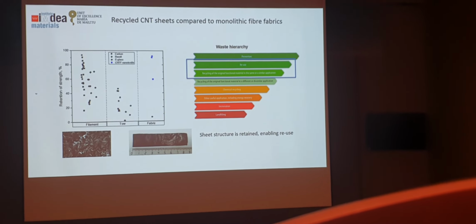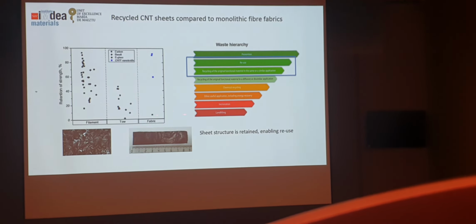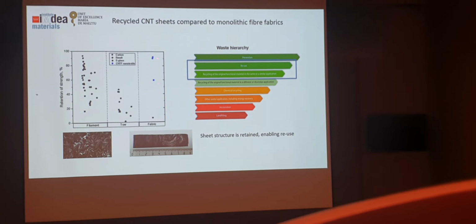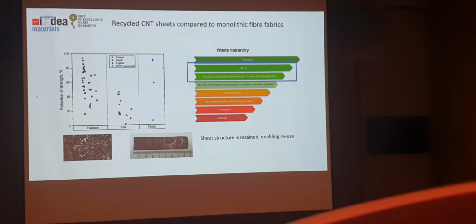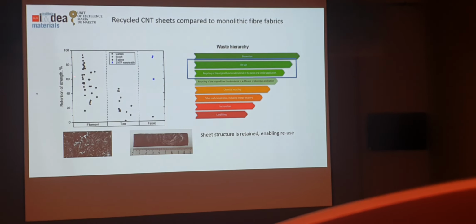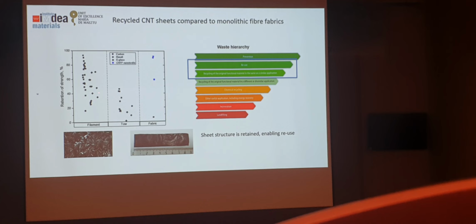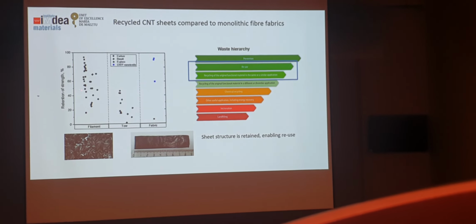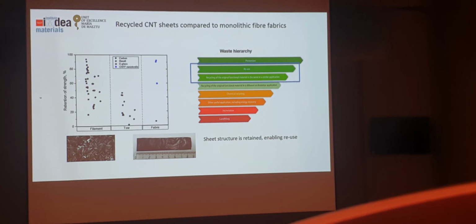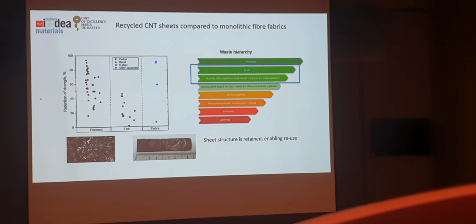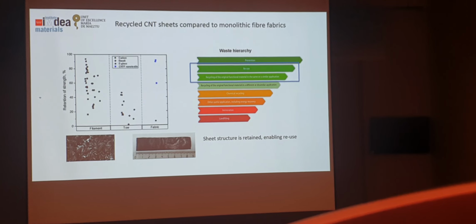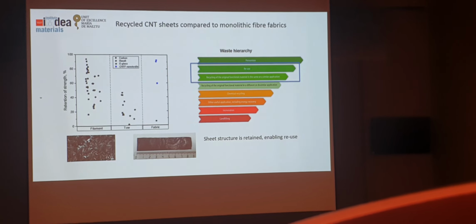Now, something we've been dealing with is how do you compare with what you would achieve in carbon fiber? And I think the best way is to say, okay, let's compare apples and apples. So these are the properties of the fabrics, and these are the properties you would get with carbon fibers as a single filament. So a lot of researchers are working on looking at the properties of the filaments, but that's just a small short fiber filaments. That's not a fabric. You can make a tow, but even that tow is not particularly good. So in a comparison of sheets or fabrics, these materials really stand out compared to the carbon fiber fabrics that people have managed to remake from these short fibers.